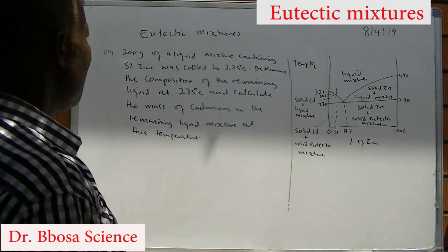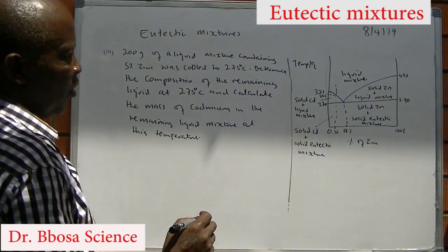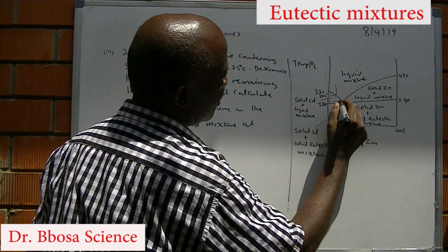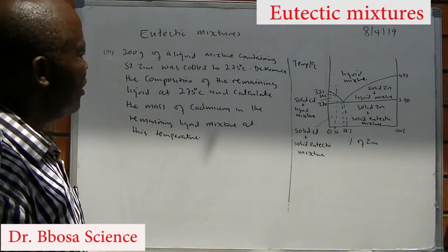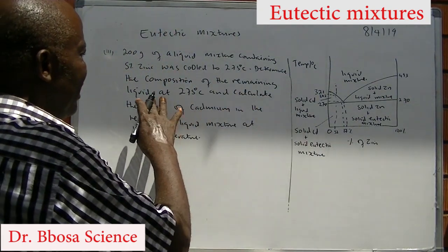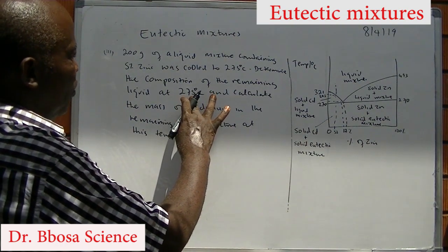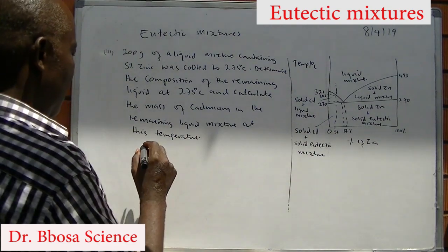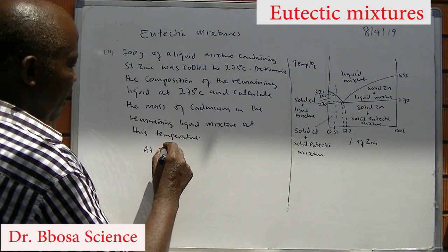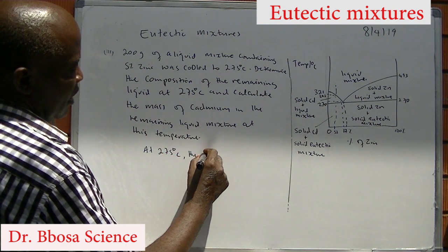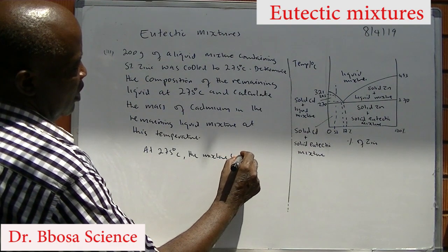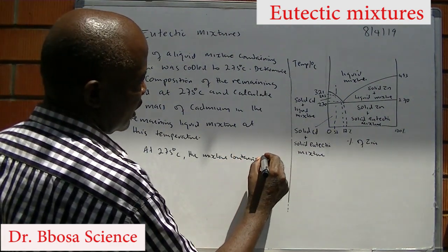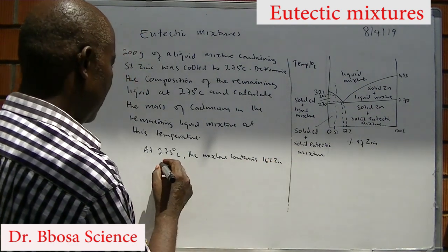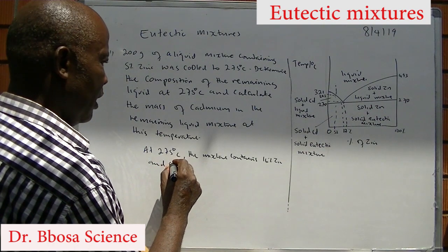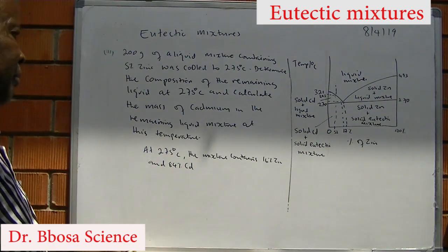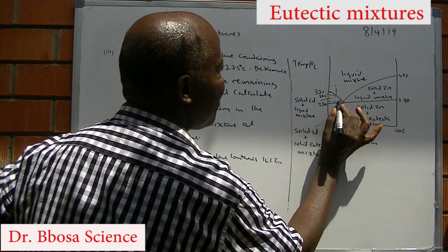200 grams of liquid mixture containing 5% zinc was cooled to 275 degrees. Determine the composition of the remaining mixture at 275 degrees. At 275 degrees Celsius, the mixture contains 16% zinc and 84% cadmium. At 275 degrees, we draw up to the curve.